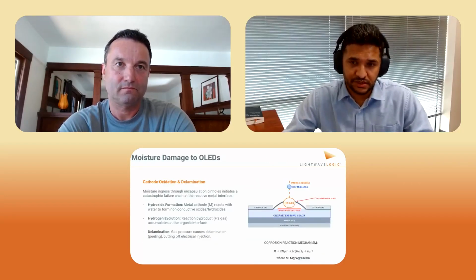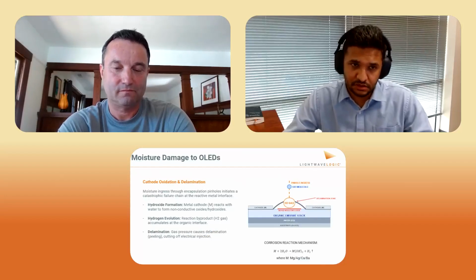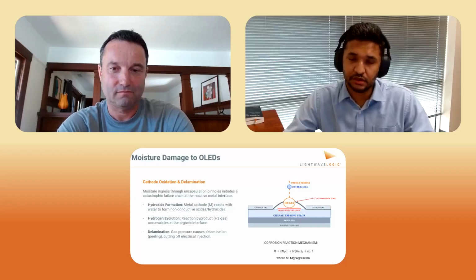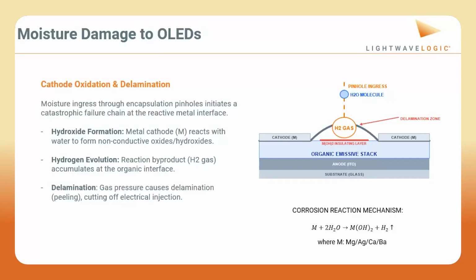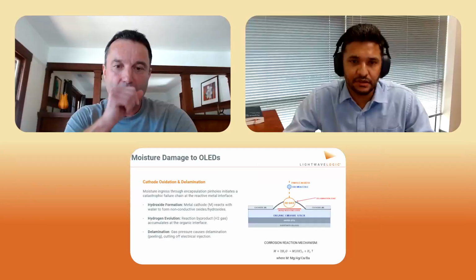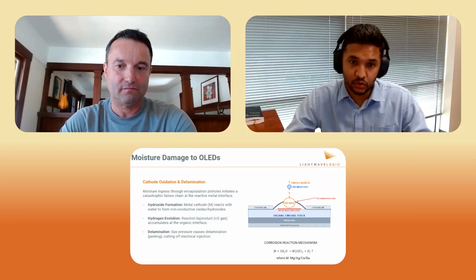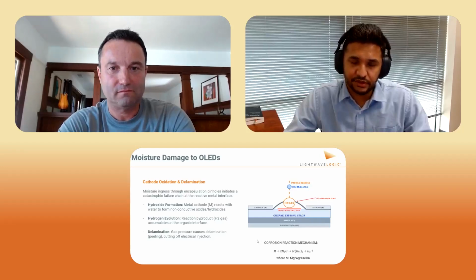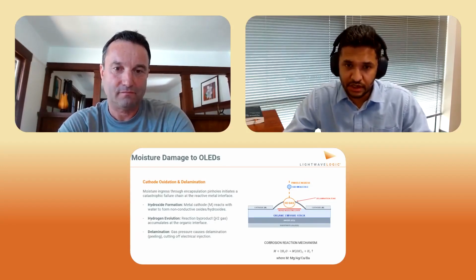The next fail mode, which I think was the biggest and most important one to solve for the industry, was moisture sensitivity or moisture ingress. Whenever any moisture gets inside and gets in contact with the cathode of this diode, the cathodes, usually made of metal, react with the water molecules and form hydrogen. When you have hydrogen gas bubbling under there, the layers separate. And when the layers separate, there's no electrical conductivity, and your diode is dead. Again, you get those black or dark spots or defects. So this was solved basically by innovation in ALD technology. And once you developed a specific ALD engineered around protecting this stack up, you then basically have what we have here.